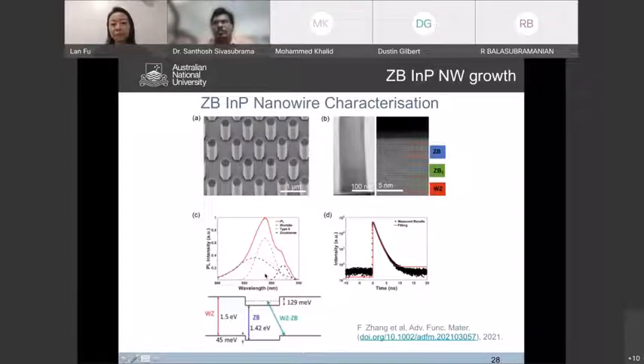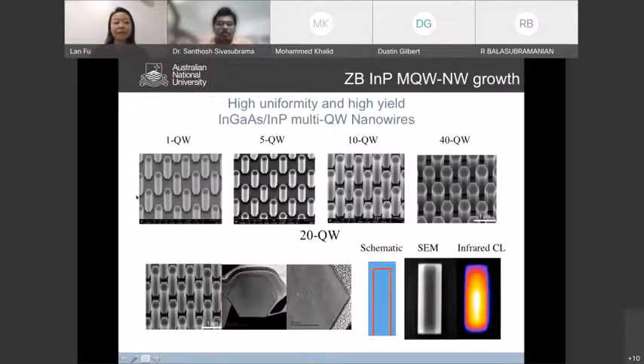Although you have quite broad photoluminescence coming from different mixed phases in the zinc blende wurtzite, the carrier lifetime is still up to 1 nanosecond, which is very comparable to our wurtzite based structure. So based on that, because of the very nice zinc blende base of indium phosphide, we're able to incorporate growth of multiple quantum wells, up to 40, with very nice uniformity, as you can see from here. And this is cathodoluminescence from those 20 quantum well structures, showing very bright and uniform quantum well emission.